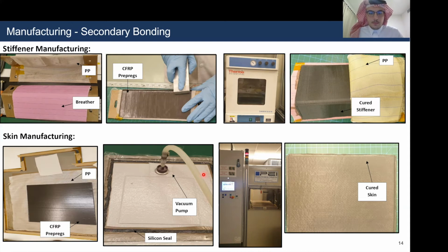A vacuum source was inserted, and this mold was then inserted into the hot press machine, and they were cured in the hot press machine with a force of 30 kilonewtons and temperature of 180 degrees Celsius for 2 hours. And the cured skin was also produced.